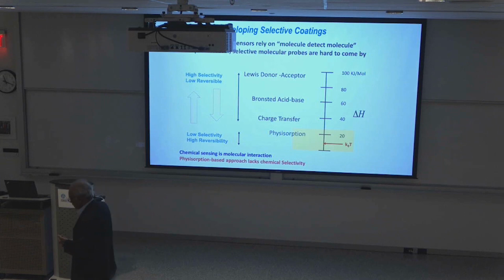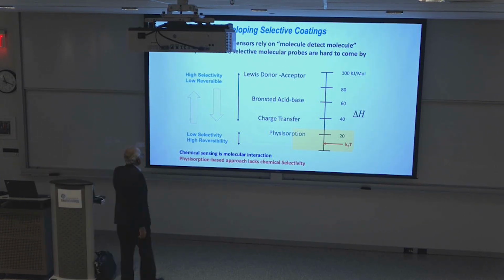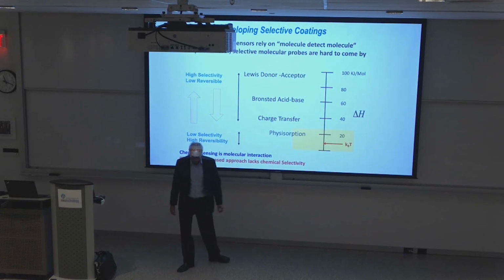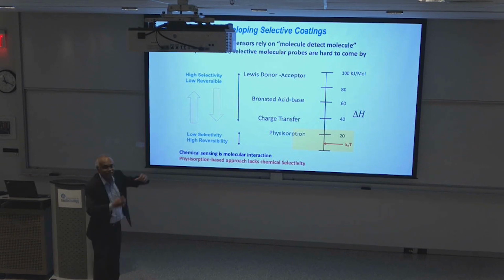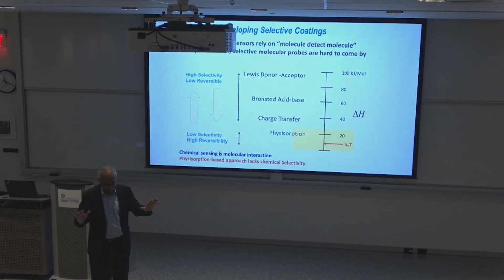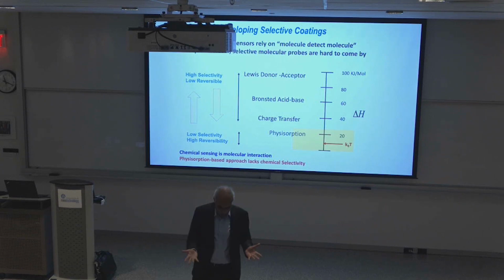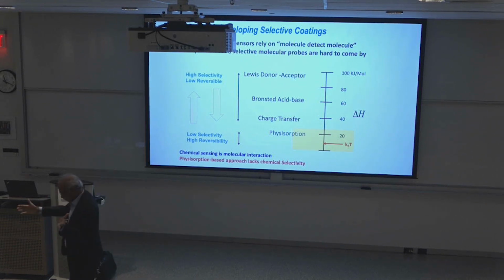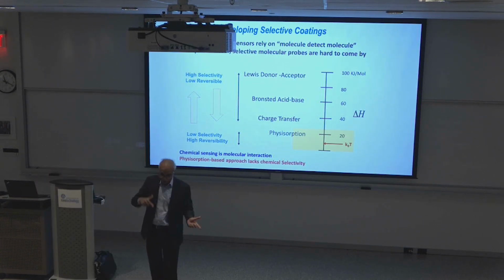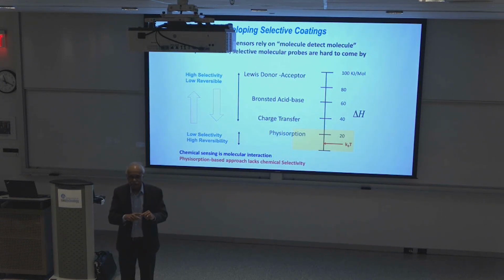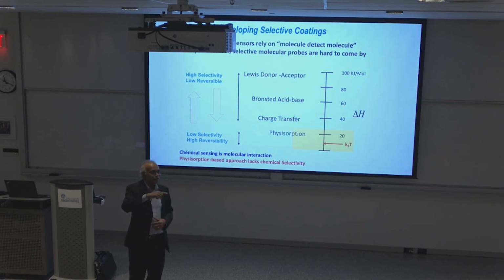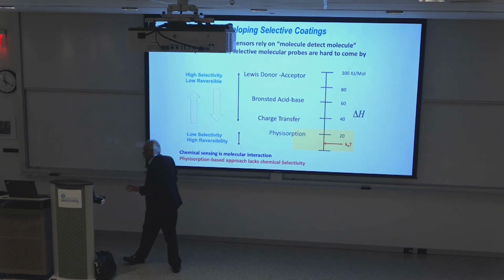We can go up in energy in charge transfer reactions and acid-base reaction and so on, but then it doesn't dissolve. Then you have to heat it. The heating is a bad idea. It doesn't really work. For example, mercury absorption: gold is excellent for absorbing mercury. Of course, it also works for hydrogen sulfide, which comes from sulfur. But if you heat it up to say 150 degrees centigrade, mercury will desorb from gold. Hydrogen sulfide, which is also an interferent, needs even 450 degrees centigrade. But you don't want to heat the cantilevers, because after some time they start bending around and then all the results become unreliable.